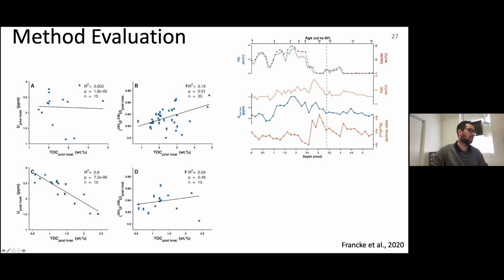And how we explain this in that scenario is basically with that hydrogen peroxide leaching, which is oxidizing all the organic matter. Obviously, we also oxidize the uranium in that organic matter, mobilizing, removing this organic matter from our bulk sediment composition without actually attacking the detrital grain, because otherwise we would see an increase in activity ratios in our sequential leaching steps. And if we then compare the activity ratio in our treated sediment sample against the TOC content in our treated organic matter, we see no correspondence at all, which then actually means there's indeed no control by the organic matter on our activity ratio.